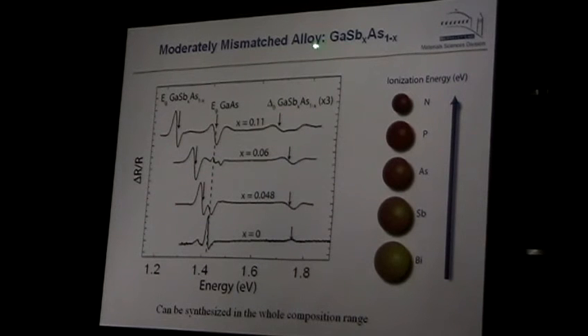So one example is gallium antimonide arsenide. When you look, they are next to each other, but there is some specific size difference between arsenic and antimony. So if you put antimony in place of arsenic, you see that the energy gap again goes down. Basically, you add more antimony. This is a composition of antimony. Band gap goes down, and it is expected because gallium antimonide has smaller gap than gallium arsenide. However, it went down much too quickly.